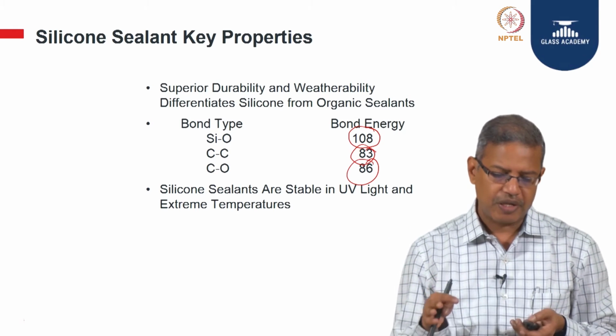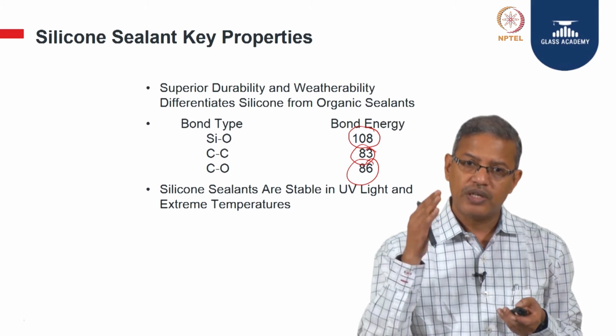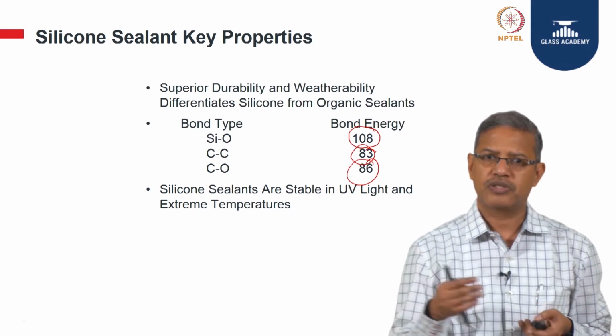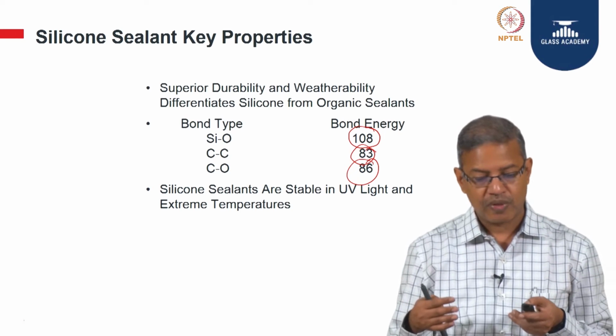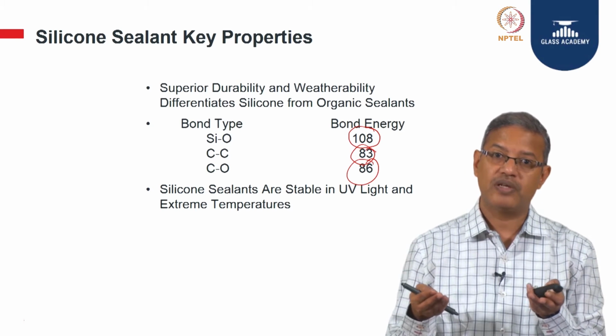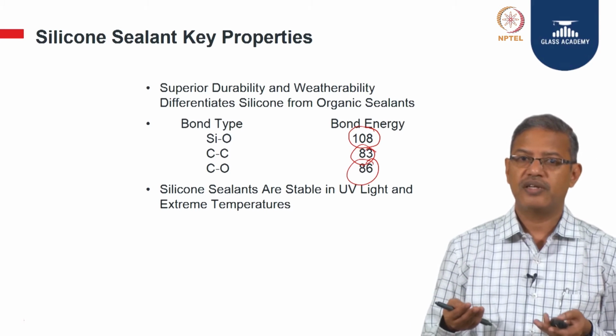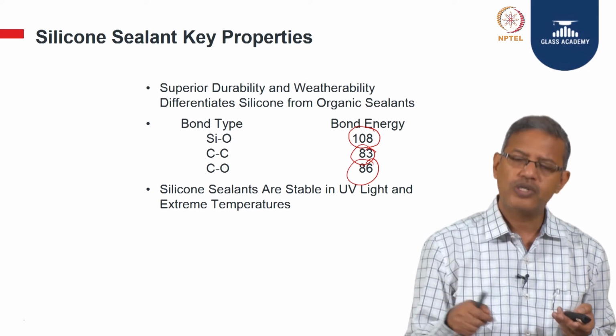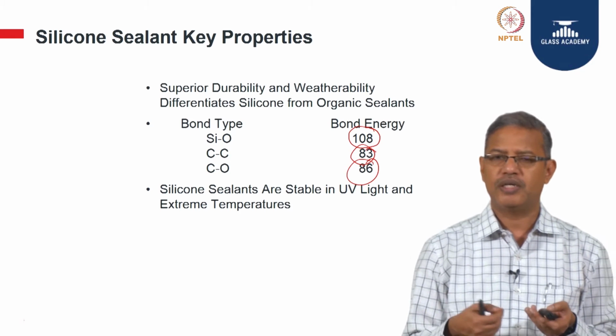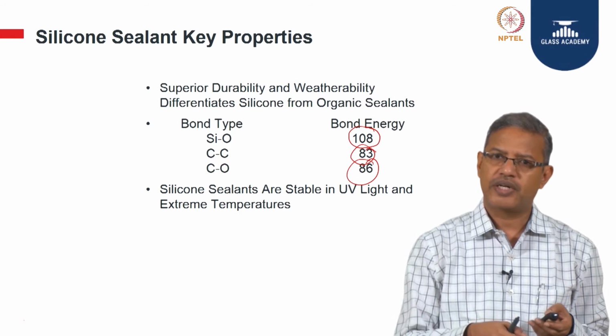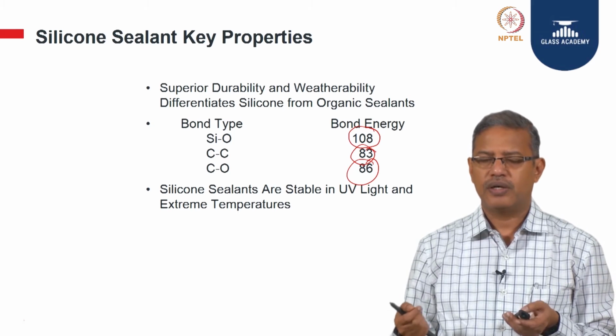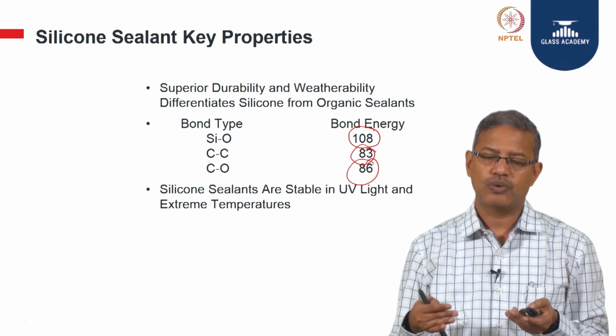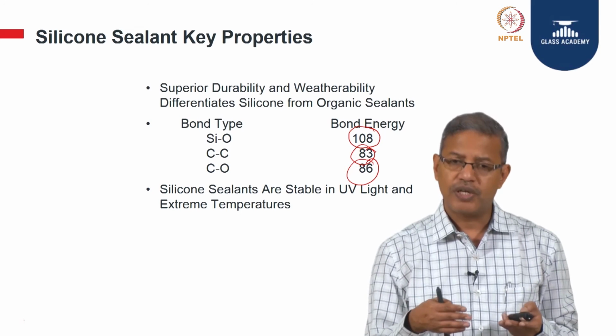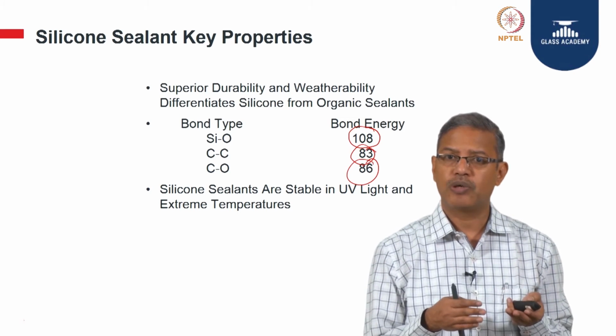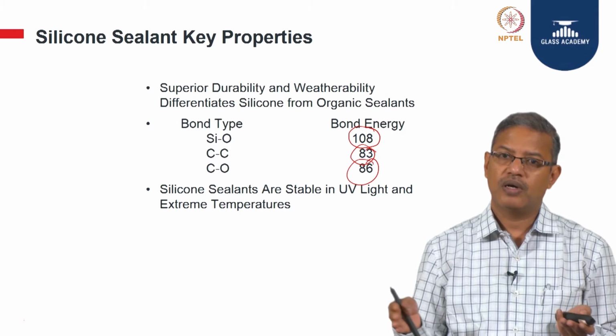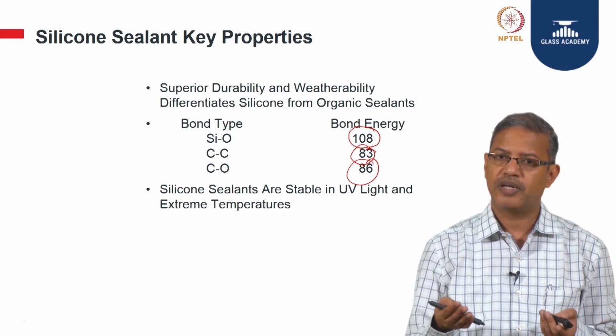When I started my career, some people were initially using organic sealants and there were tremendous failures. I attended a few of them, thinking that these were probably silicone, and when we did an analysis, we found that the product was oozing out so much oil, did not have durability, did not have good bonding, and came out like a gasket. That was a big challenge. In a climate like ours, we need to think completely about long term durability, and silicon has proven that, and we have case histories running in India for 25 years now.